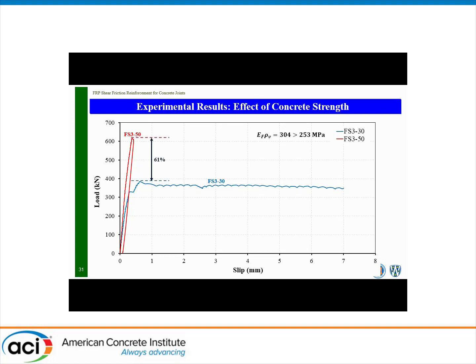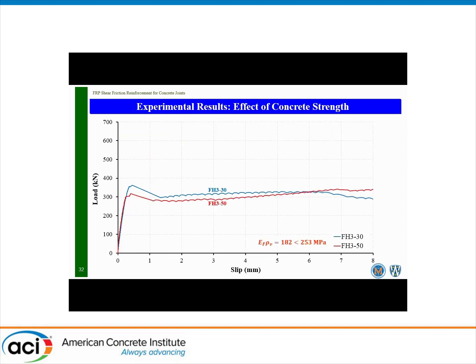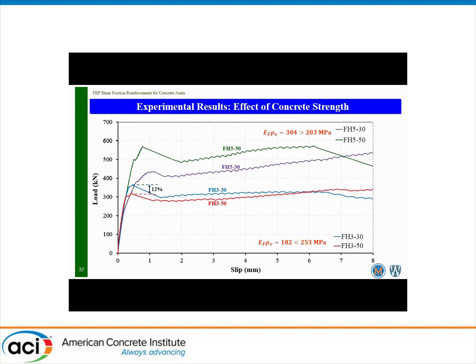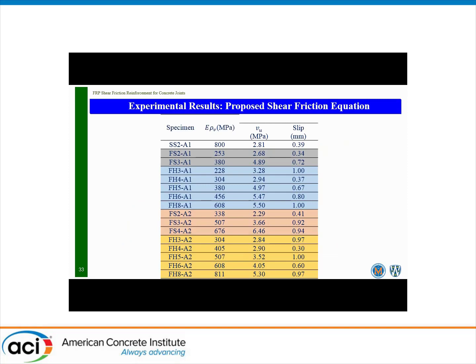You can expect up to 61% increase in the stiffness. The same for the headed bars: 3 for 30 megapascal, 3 for 50 megapascal. There is no big change comparing the effect for low strength concrete, but for high strength concrete, there is a significant increase with the increase in the content of the GFRP itself.